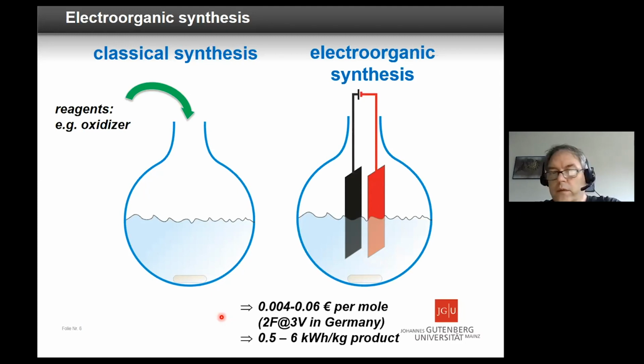And if you do so, then you see in euros, you need here per molar conversion. That means 2F. That's a reasonable assumption that you make a bond. You need 2 electron equivalents, and a relatively conductive system. That means the applied voltage is 3 volts, and this corresponds to the molar amount. And most reagents are much more expensive. This corresponds as well, if you think about kilogram product, to 0.5 to 6 kilowatt hours. This is if you do methanization. This is if you have a polymer system.